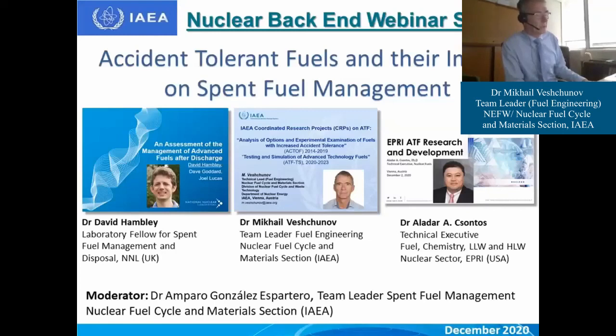Not only that. Of course, if we go further to higher severe accident conditions, you can read in KIT presentations, for instance, recent presentations at different meetings, where they observed very strong oxidation of silicon carbide at 1800 centigrade. So all these new materials are more or less maybe better than zirconium under normal operation conditions, not bad for local conditions, but they are still under research for severe accident conditions. And of course, eutectic formation is one of the important topics.